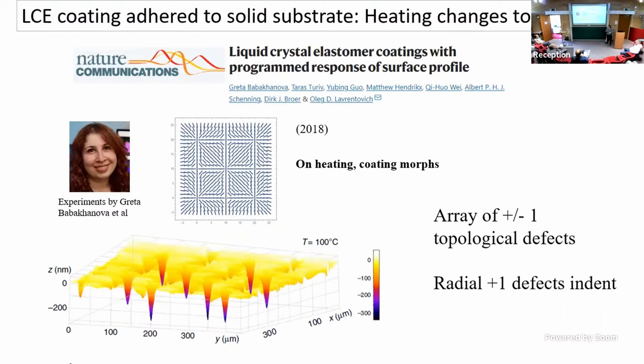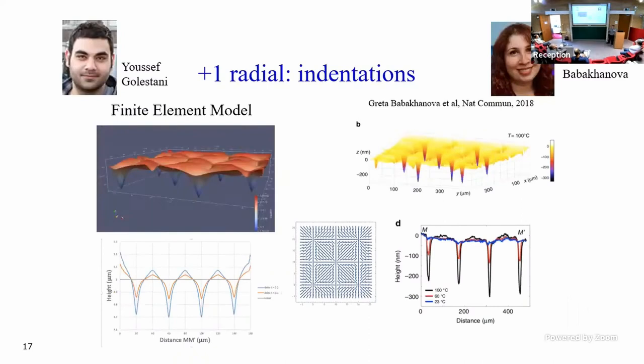And when she heats it, every one of these plus one defects turns into a little dimple indentation. And there's minus one defects too, so we have plus ones and minus ones. Let's see what happens. My student, Yusuf Golestani, was dying to model the system. So he put that microstructure into our simulation and got exactly the same kind of structure. Everywhere there's a plus one defect, you get an indentation. If you put the temperature back where you started, it disappears again. So this is a reversible topographic transition.